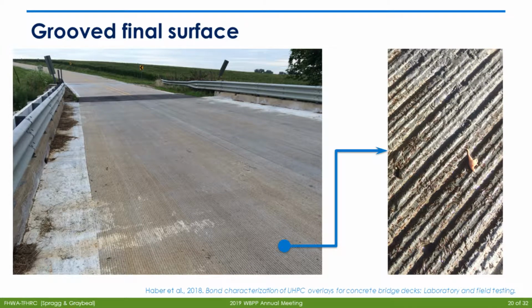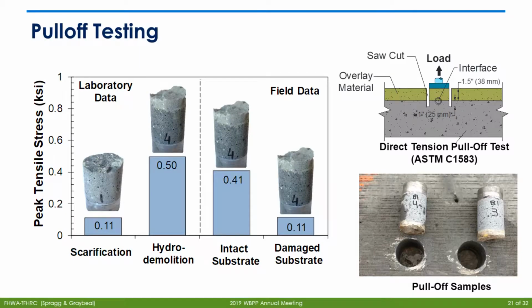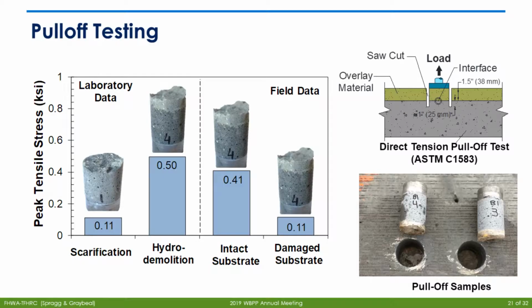So we were able to go out to visit this project and bring back some samples and do some testing in the lab. One of the main things that we're concerned about with overlays is how well the overlay has bonded to the substrate concrete. So sometimes you could imagine using a bond enhancer or some epoxy-based bonding agents. UHPC has a relatively good bond strength or bond characteristics, but we were confirming that with what we've called a direct tension pull-off test. A picture of that is up here in the top right corner.